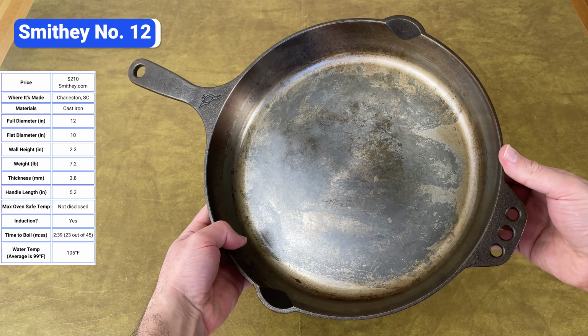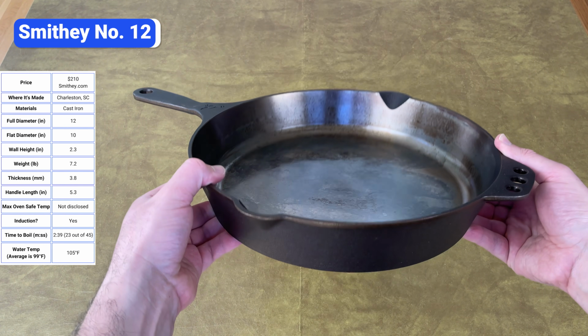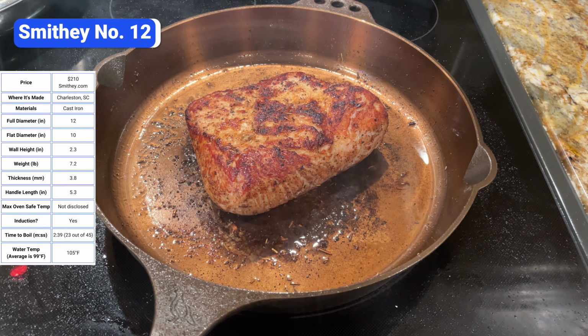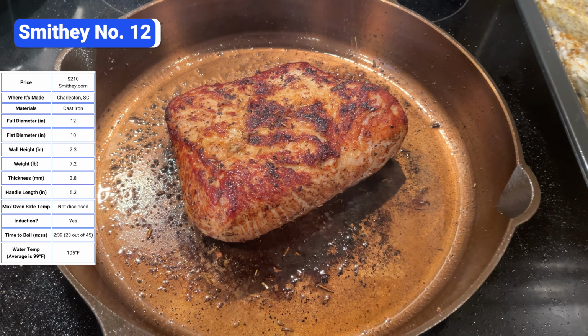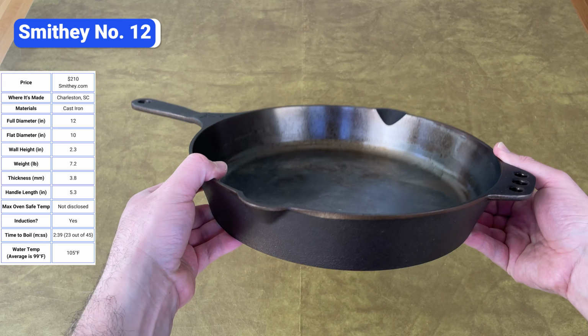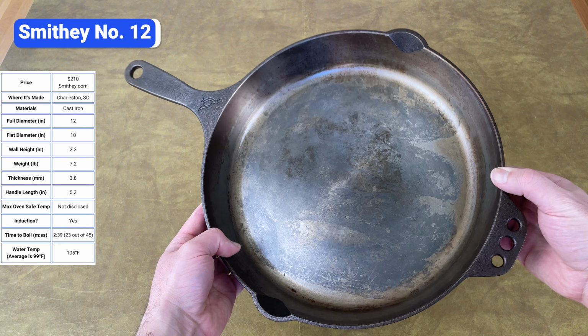Smithey is expensive for a cast iron pan, but it has a smooth surface that prevents sticking. It also has a thick bottom that holds heat incredibly well, which is ideal for searing and browning. My one complaint is that the initial seasoning quickly wears off, so you need to re-season it right away.